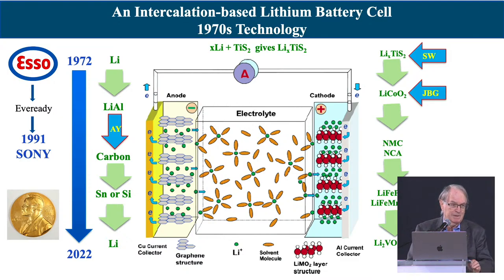What made the batteries in the end economically successful is the work of Akira Yoshino, where he showed that you can use graphitic carbons, as shown in the picture here, where you can store the lithium between those sheets. But it has a big penalty. You need 72 grams of carbon to store 7 grams of lithium. The graphite also takes up half the volume of the cell. So if we are to make progress, we've eventually got to get rid of all that carbon.